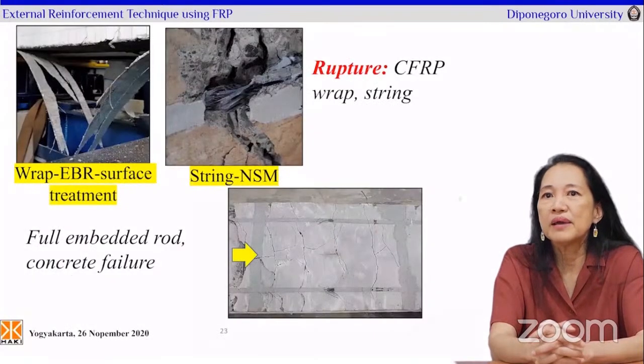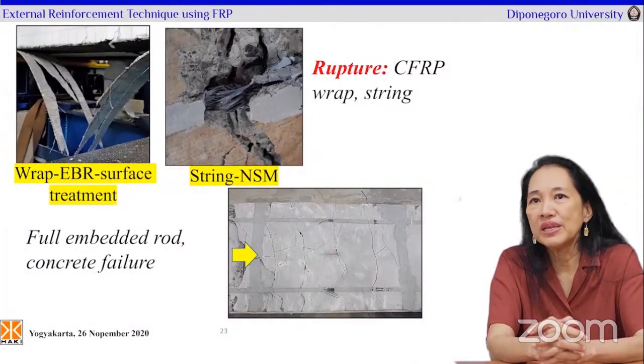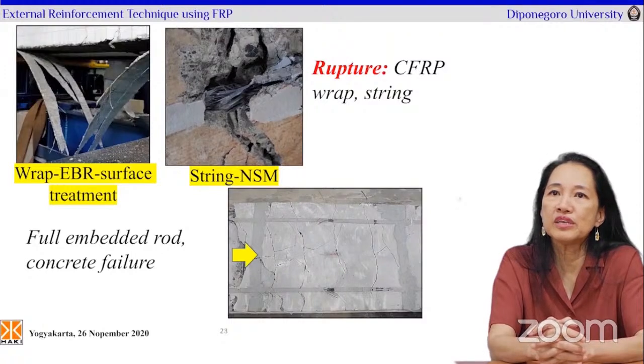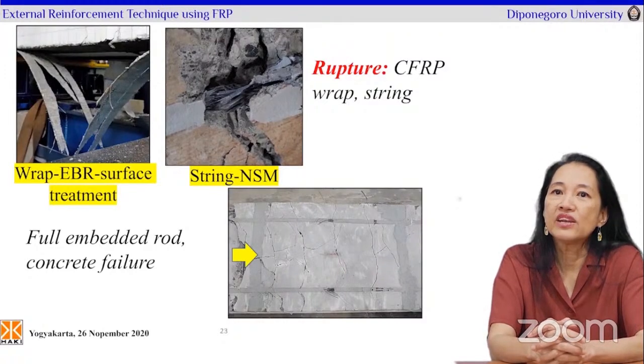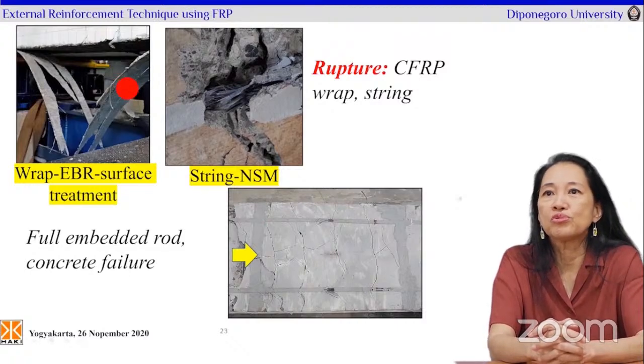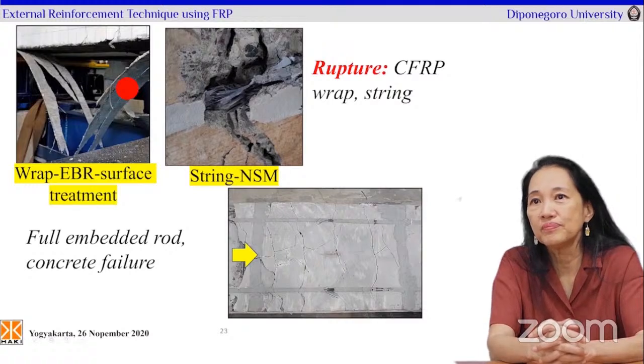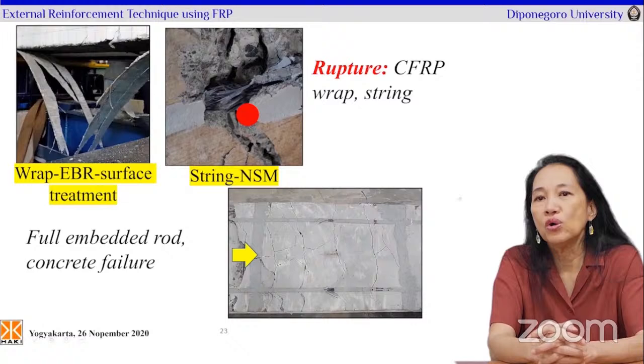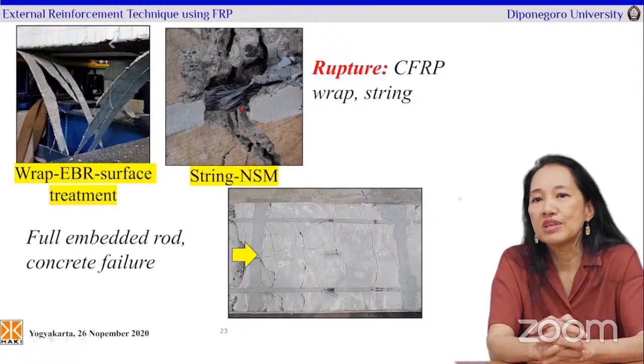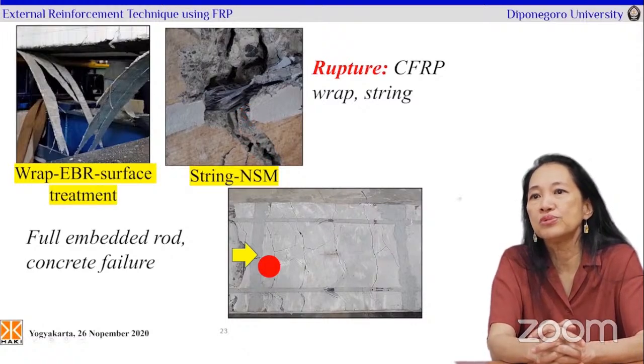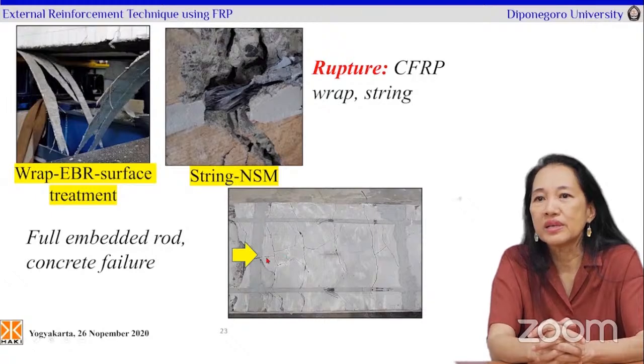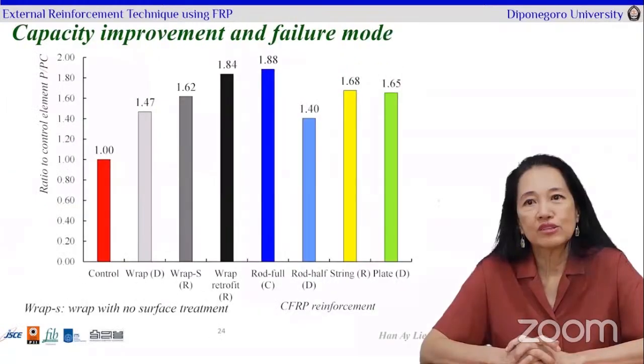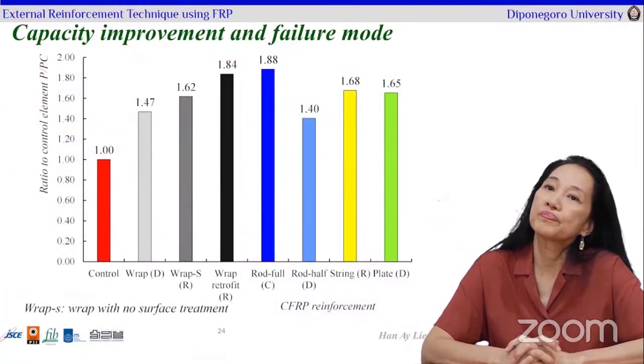As for the other samples, we then increased the performance of the surface to increase the bond. And now you can see that the FRP wrap was ruptured. This also happened with the string. You can clearly see that the string was broken. And only for the rod that was embedded in accordance to the ACI code, we had concrete failure. Let's now look at the results.